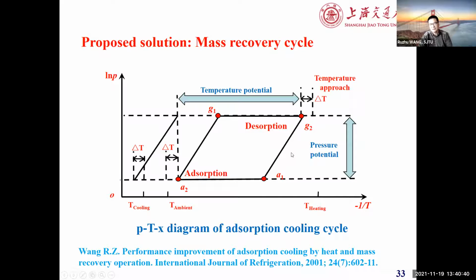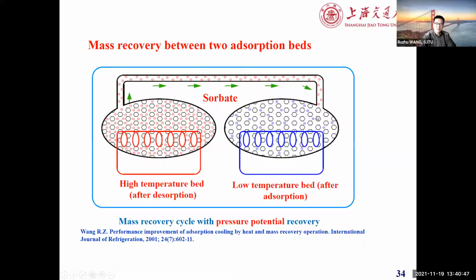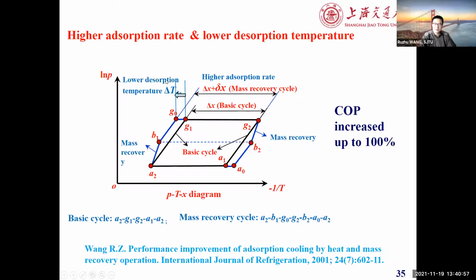That's 20 years ago, but it was the first to demonstrate how mass recovery could work. So this just shows that we changed the process. We just open the valve of the two beds, and then you get the vapor recovery to a medium pressure. So you get more desorption and more adsorption. In this case, you could increase COP. It could be possible for a 100% increase.